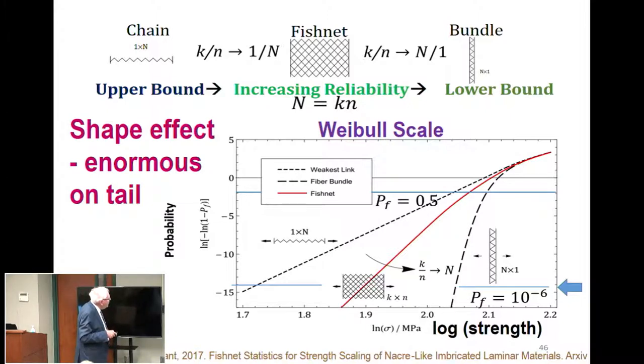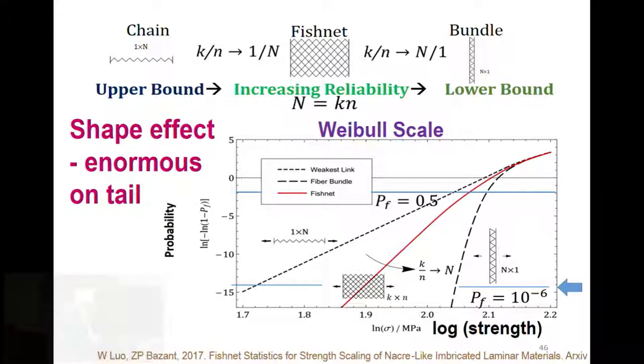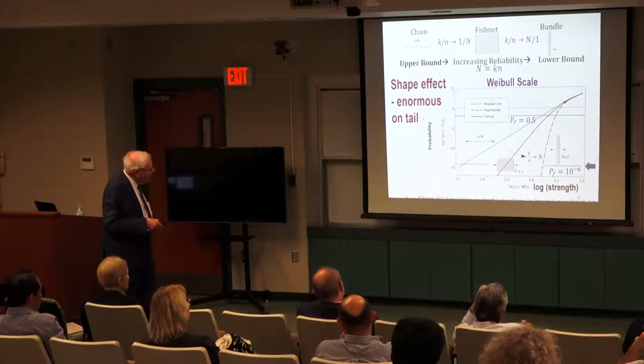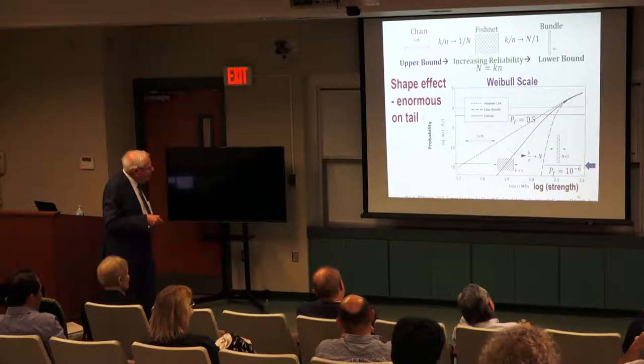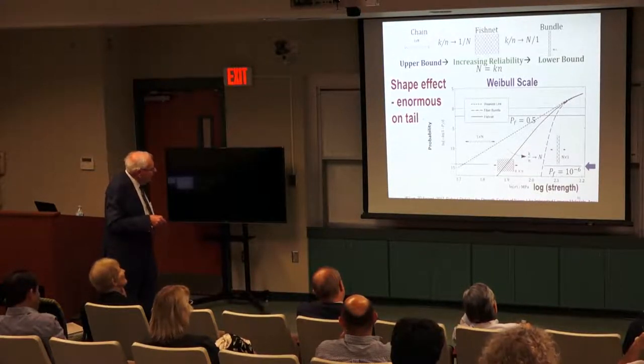Two rigid plates and fibers in between. The opposite, if you extend it longitudinally, you get a chain. So fishnet statistics provides a continuous distribution from Weibull to Gaussian distribution. That's shown here, schematically. If you change from a chain to a bundle, this is how the distribution changes in Weibull scale. This is Weibull distribution, and this is Gaussian distribution in the same scale.